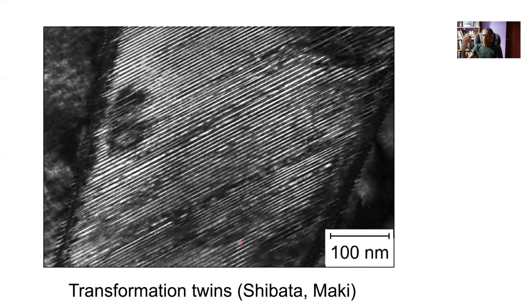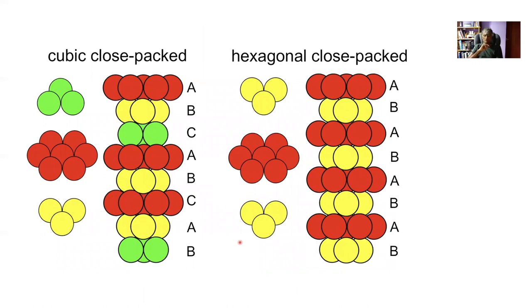There isn't just one martensitic transformation that occurs in steels. We've talked about FCC to BCC or slightly body-centered tetragonal lattices, but you can also get hexagonal close-packed martensite in alloys of iron. This is a much easier transformation to understand because the close-packed planes inside the austenite are arranged in ABC ABC stacking with a repeat period of three, and to change that into a hexagonal close-packed lattice involves simply changing the stacking sequence to AB AB AB with a repeat period of two. On every second plane we have to pass a dislocation which changes the stacking sequence from ABC to ABA.